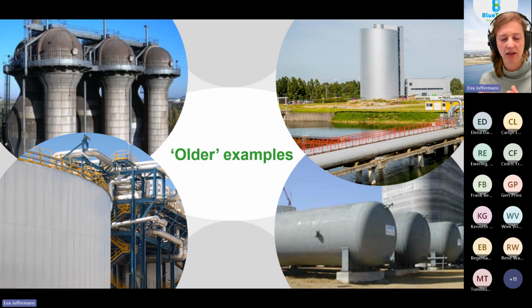So at one point they will heat up the ceramic storage medium using the excess flue gases, and at the same time use another ceramic medium, which was heated up before with the excess flue gases, to heat up the ingoing flue gases. And this process is changed in direction every few hours. So this is already an hourly energy storage at high temperature, which is often deployed in those sectors.